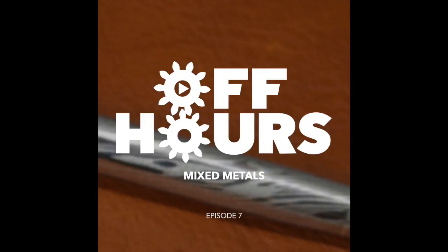Yeah, and so the other tradition of metalwork that has a similar effect is mokume gane, which is a Japanese technique of fusing different metals together, and these will be non-ferrous metals. So typically it's copper alloys, gold, silver, brass, things like that, and you fusion weld those together in multiple layers. And then again, as you twist them, as you draw them out, as you distress it and reveal layers underneath and then compress it again, you end up with a grain structure that looks again like wood grain. You can then apply different etchants and patinas that will affect some metals more than others, and it will really bring out that grain structure quite nicely.